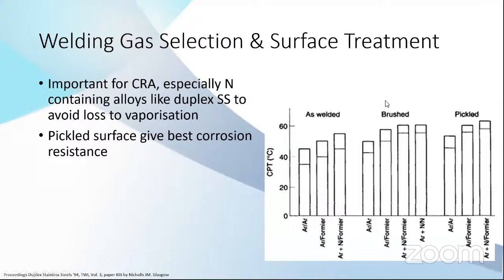Going to the right is the surface treatment. The cleaner the surface, the higher the corrosion resistance of the material. So again, if possible, if you're welding a big pipe, you can pickle the material. But sometimes you have to be satisfied with the as-welded one. For example, when welding a small pipe, you cannot pickle the inside of the pipe, so you have to settle with this one. But the variable that can be adjusted is the gas. You can modify the gas to give better corrosion resistance.